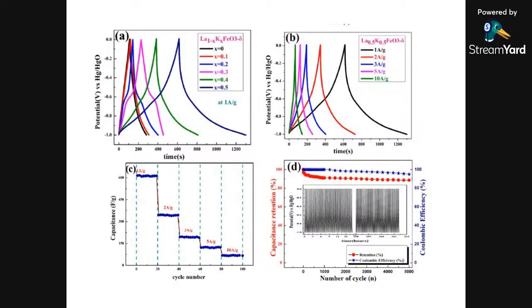You can see here the charge-discharge time gap is close to this one. At 1 ampere per gram it is up to 1300 seconds. So up to 10 minutes it's getting charged, and almost 10 minutes it's getting discharged at such a high current. And the capacitance is also close to 600 farads per gram.